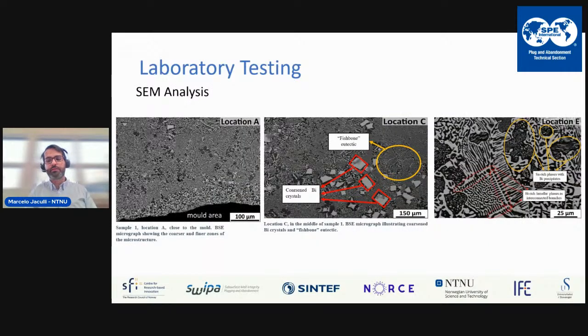Another study that we also carried out was regarding microscope analysis for the microstructure. It's not really my field here, but we have done some tests with the plugs after they solidified, and then we could identify the microstructures. By seeing finer grains, you are expecting better properties. When you see these coarse grains, these crystals of bismuth material within the tin, then you expect this to not have as good properties as the other case. But that's a separate work here that you could check in our publications.